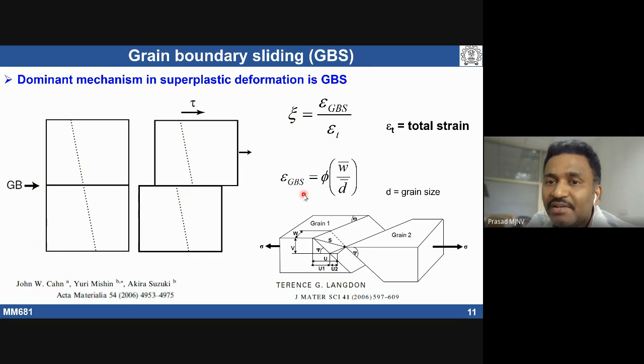Grain boundary sliding strain is calculated by taking the average change. Assume that you have multiple grains in a polycrystal, with so many boundaries. We know which boundaries contributed to grain boundary sliding, so we can know the change in the sliding width. That average sliding with respect to the average grain size is taken as the strain due to grain boundary sliding. In region 2 of superplastic deformation, the zeta value is going to be greater than 50%. That means if the material has experienced, for example, 1000% elongation, more than 500% strain is coming from grain boundary sliding activity.